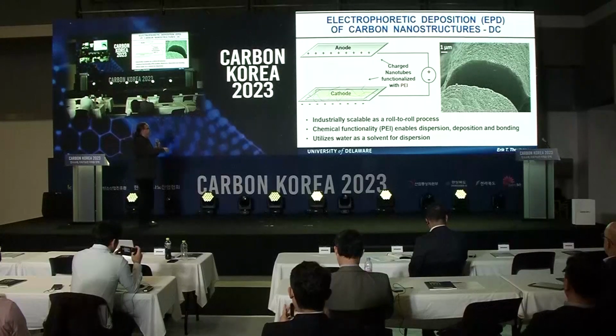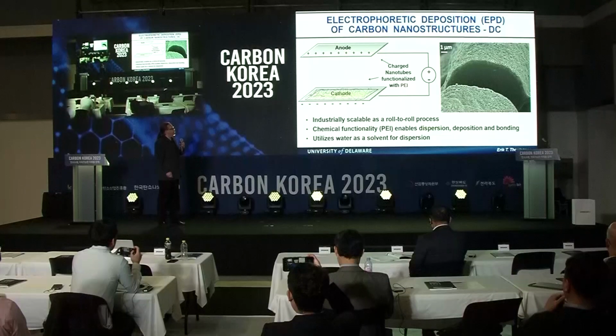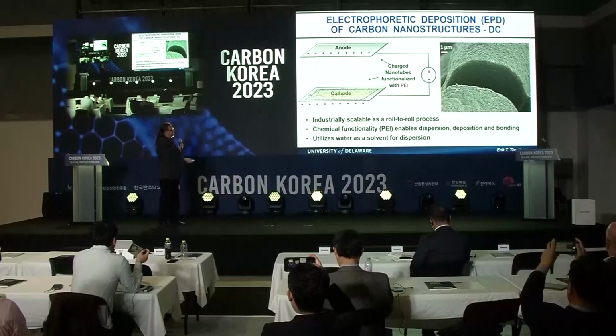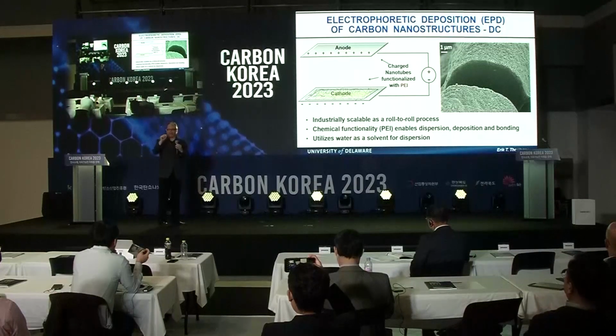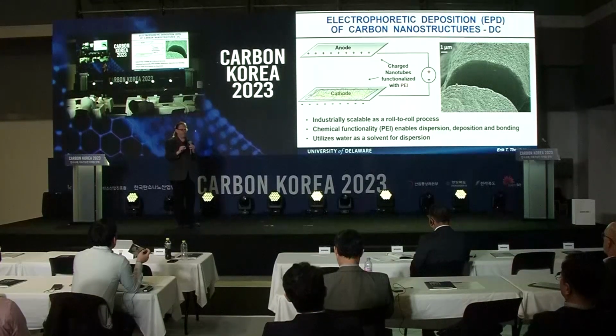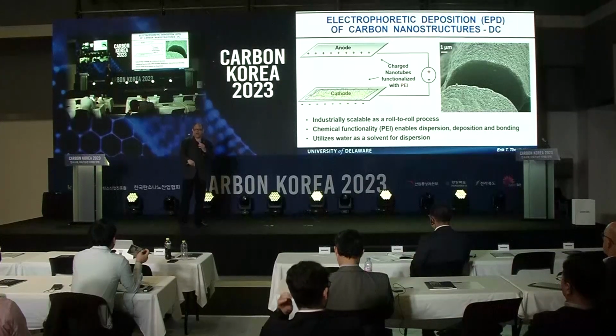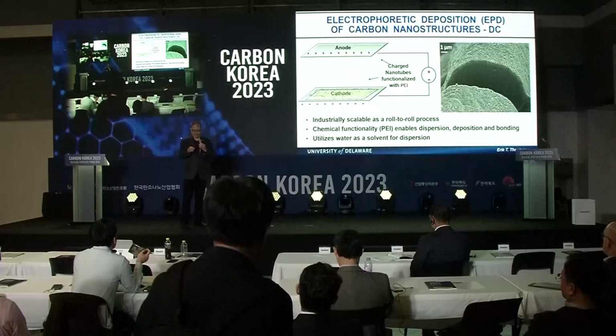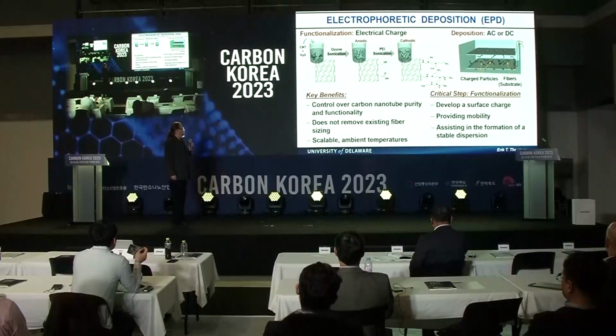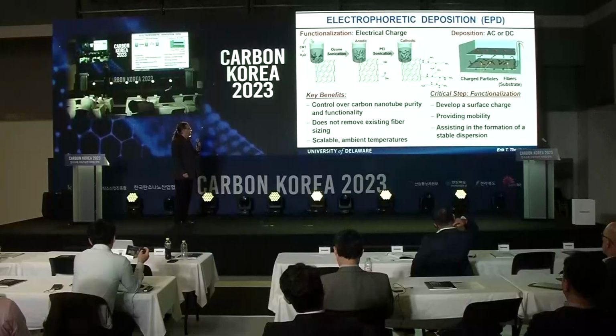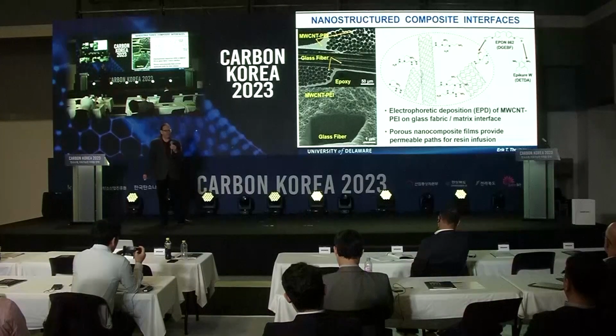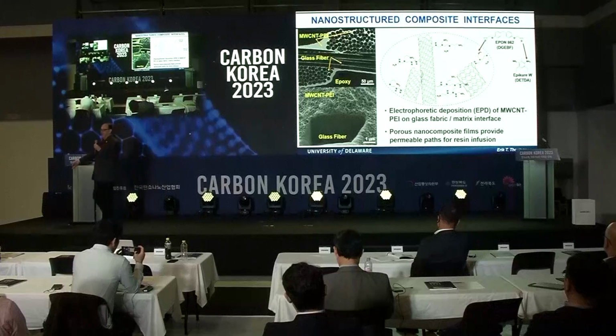What you see on the right-hand side is where we've cross-sectioned a fiber, and at the very top of the fiber and surrounding the fiber is almost a sponge-like coating, and that is the carbon nanotubes that are functionalized. Those carbon nanotubes bond to the surface of the fiber, and they also bond to each other, so they're fully integrated. In our case, we can control the process. We have a lot of control over the purity and functionality. And really, it's that surface charge which not only enables the process, but those chemical functional groups bond to the surface of the fiber. I think our original interest was in modifying the fiber matrix interface in traditional composites.